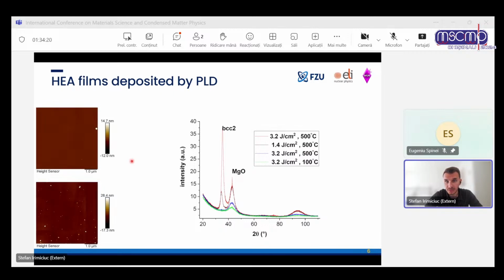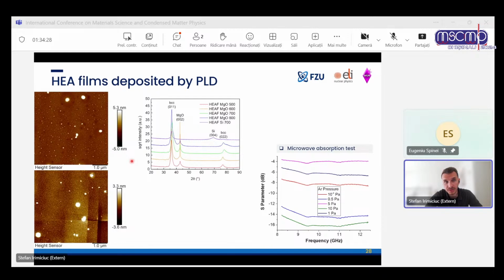Then here again we confirmed this for the deposited films, and we also tested the deposition temperature, and we saw that above 500 we get the BCC phase. So there are chances for epitaxial growth. And to end on a maybe positive or promising note, we also tried the microwave absorption test for the films. So we're one step towards the application that we wanted, and the results were,